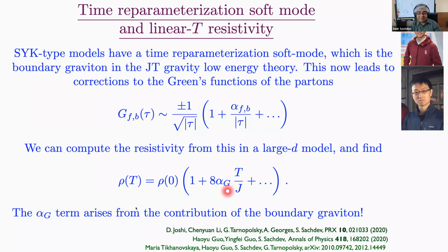Okay, so what I was just going to say, this is, as far as I know, really the first model where anybody has found linear resistivity down to 0 temperature. I mean, you can get linear resistivity at high temperatures, but this is at least in this large M limit of SU(M). So there's like a double scaling limit here. First, you take large N, and then you take large M, which was actually already present in my first paper on this topic in '93. It's the same type of scaling limit. And for the t-J model, it gives you this linear resistivity. I mean, we didn't understand this correction term in those days by any means. And now we can look at this correction and it gives you exactly what you see.